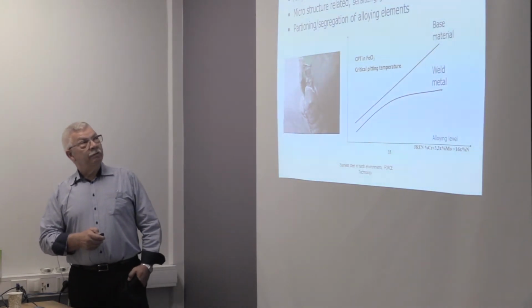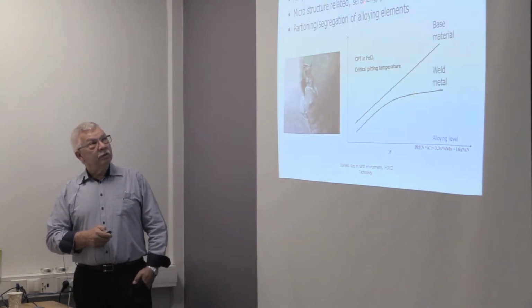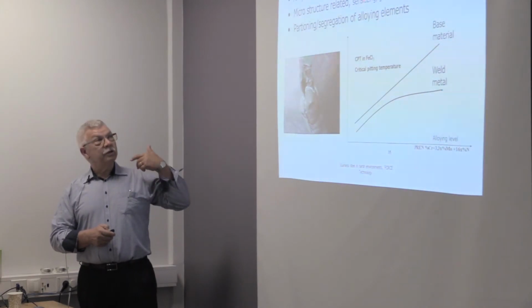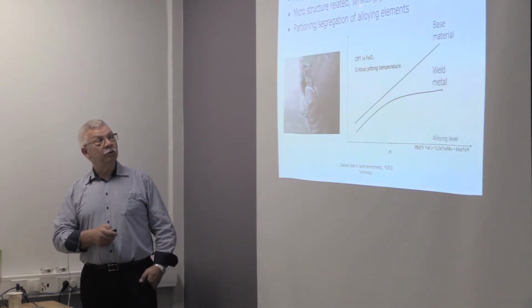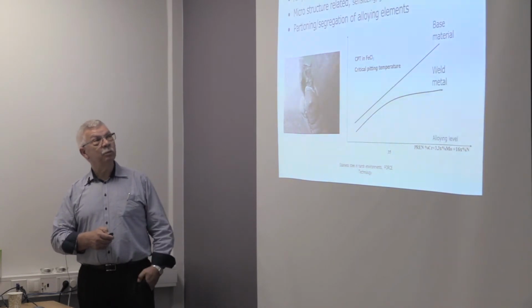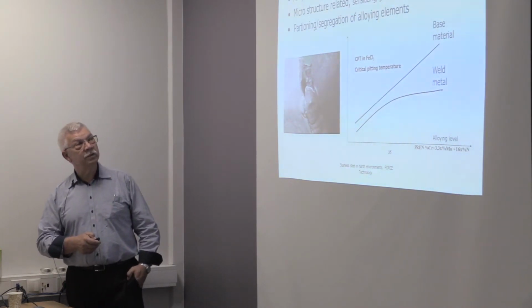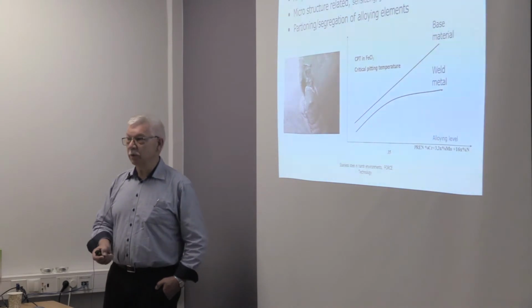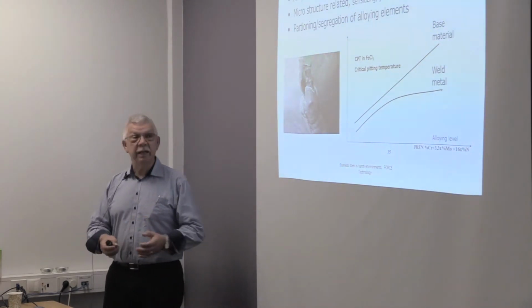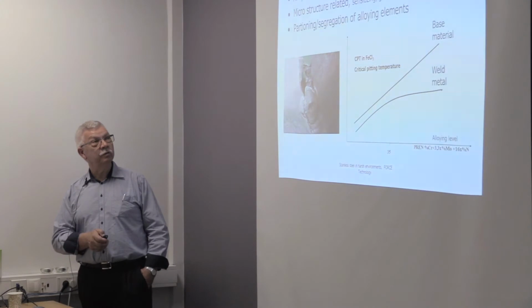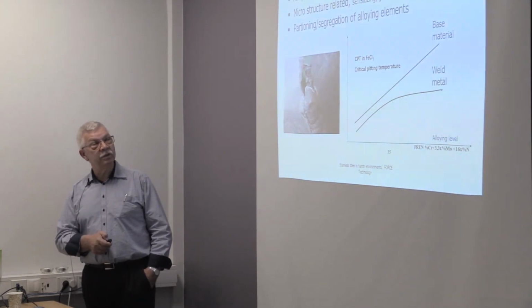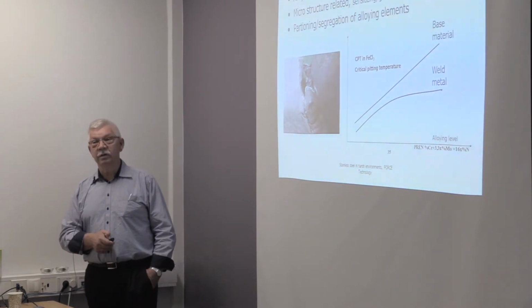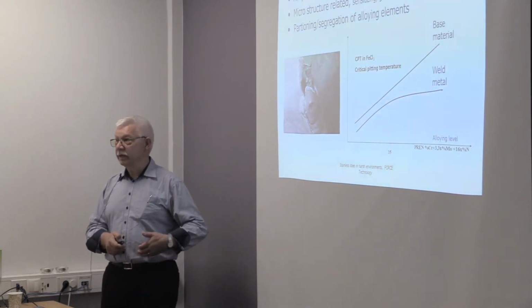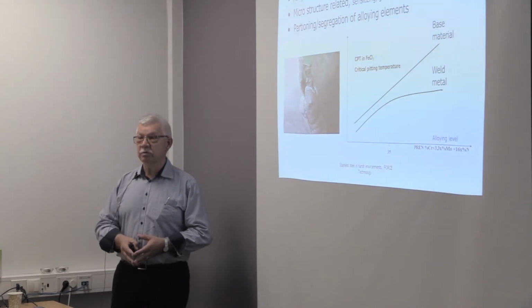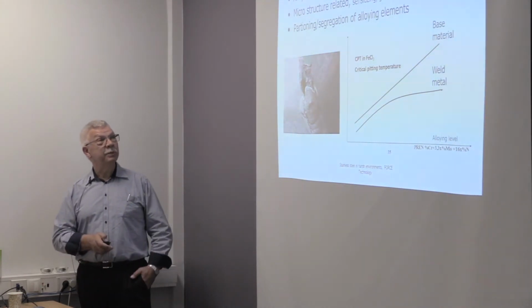We might also have something in the structure which made it sensitive to corrosion. I'll come back to that in a moment. We might have galvanic couples, where some part of the structure will be noble to others, and that would cause corrosion to happen. We might have problems in the duplex stainless steel with phase balance. If we have too much of either ferrite or austenite, we will have corrosion resistance which is not meeting the base material.